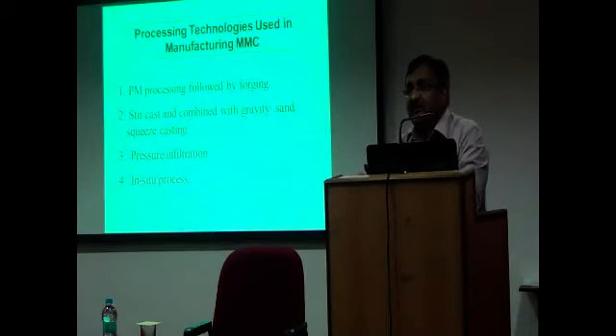So now, how do you make this? You have two constituents: the reinforcement, like silicon carbide, graphite, or alumina, which is a ceramic constituent, and a metallic material like aluminum or magnesium. You know, normally aluminum is melted in an alumina crucible because it doesn't wet. A similar problem will come into the picture if you try to combine these two, what you call mismatching constituents.